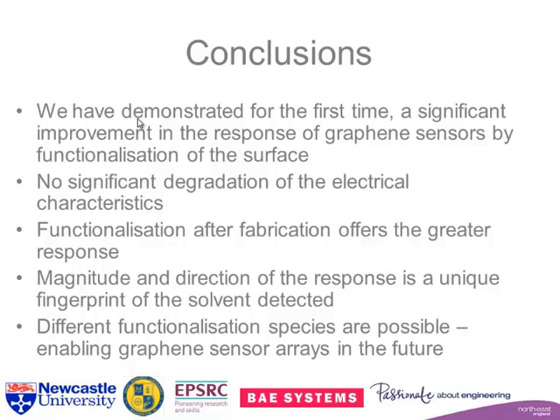The next challenge will be mixtures, just in case anybody's thinking of that one. And we actually now have the ability to do different functionalization. This is all oxygen. We have process recipes for fluorine and amine groups because we're looking at moving into biosensors in the future. The sensors themselves are stable to 400 degrees, although we can't detect solvents at that temperature.